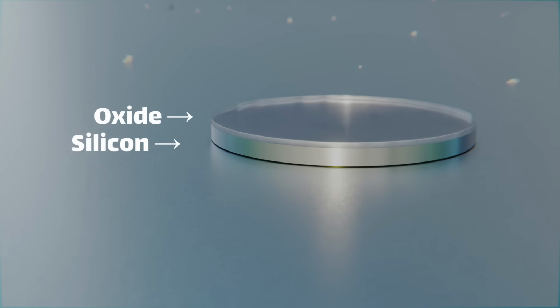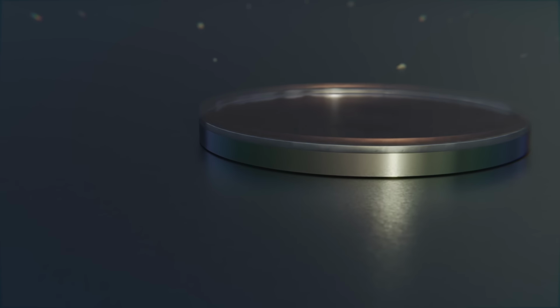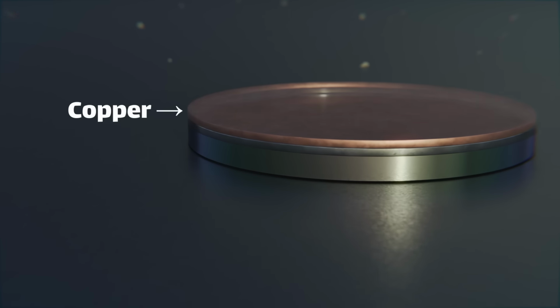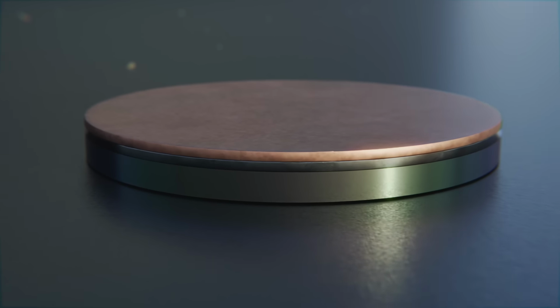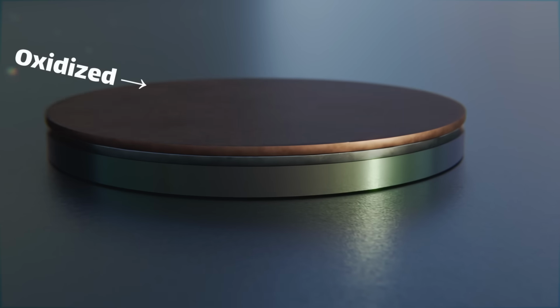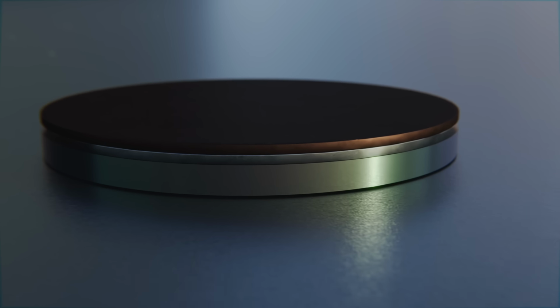We could, of course, just use a different substrate and skip all of this initial prep. But silicon is just convenient. It's very flat, relatively cheap, and the insulating oxide is easy enough to grow. Next, we deposit a thin layer of copper on top using magnetron sputtering. I'm depositing 80 nanometers of copper for all of my tests. Then, we oxidize the copper to make our semiconductor.